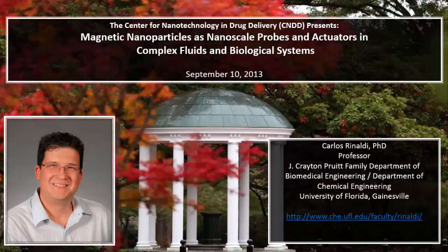For nanoparticles, a similar phenomenon was reported in 2007, where they looked at cadmium selenide nanoparticles in polymer melts using something called X-ray photon correlation spectroscopy, basically dynamic light scattering with X-rays. You can do that at the Argonne light source. And what they did is they suspended particles in polystyrene of a single, high enough molecular weight, and they measured the diffusivity at 4 different temperatures. They measured the viscosity at that temperature, calculated the Stokes-Einstein diffusivity, measured the diffusivity, and they found that always the actual diffusivity was 2 orders of magnitude higher than the diffusivity calculated according to Stokes-Einstein.